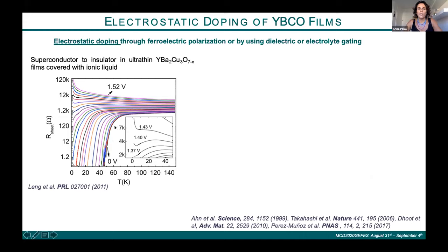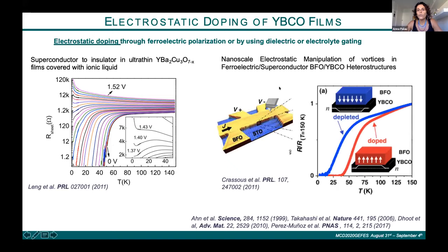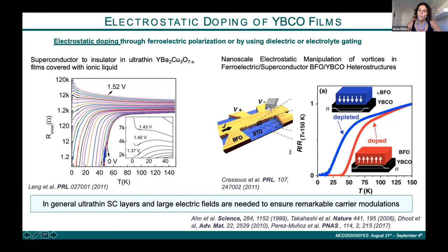been used. For example, in this work performed by Leng et al., they used a very ultra-thin film of YBCO, which was covered by an ionic liquid, and the ionic liquid gate was used to induce this transformation of the material from the superconducting metallic phase to the insulating phase. Other approaches used ferroelectric material. For example, in this work performed by the group of Javier Villegas, they used BFO, a ferroelectric material, covering